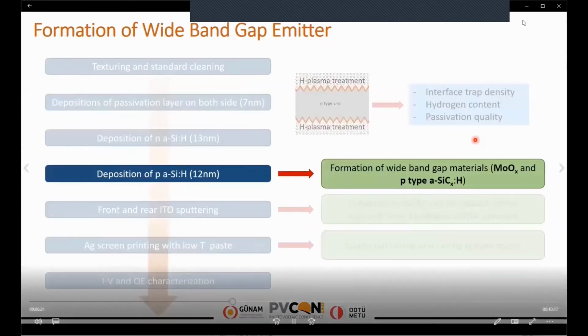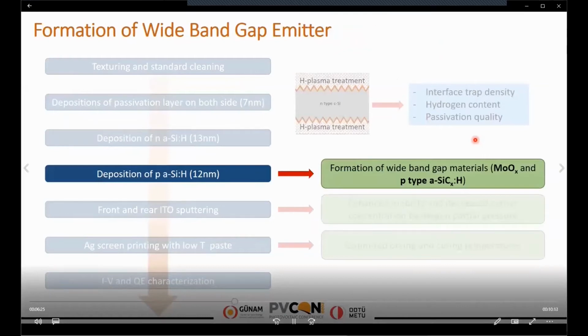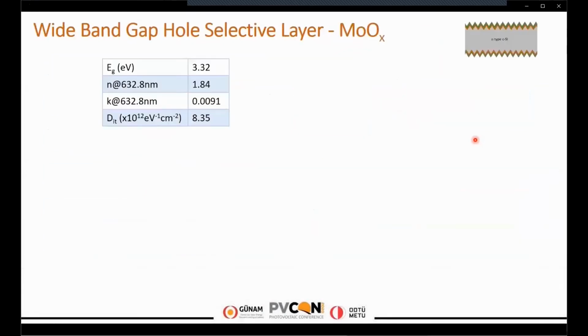Now I would like to continue with the two wide bandgap materials. So let's start with molybdenum oxide. The molybdenum oxide layer has a 3.3 electron volt bandgap value, but by itself it has a very high interface defect density, so it is not a proper material to use as a passivation layer.